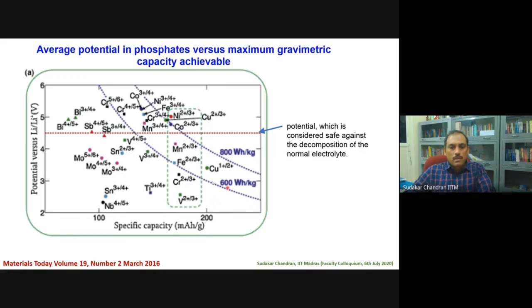These two lines here show the 600 watt hour per kg specific energy density. Typically, they wanted something more than 600 then. So iron and manganese were found to be the suitable materials. Of course, cobalt and nickel versions also were shown, but they could not be used because it is beyond the potential where you can safely operate the lithium ion battery. Anything beyond this, the electrolyte would undergo